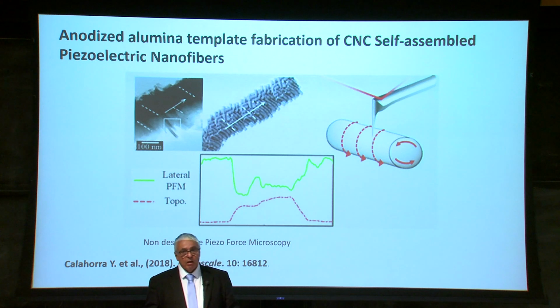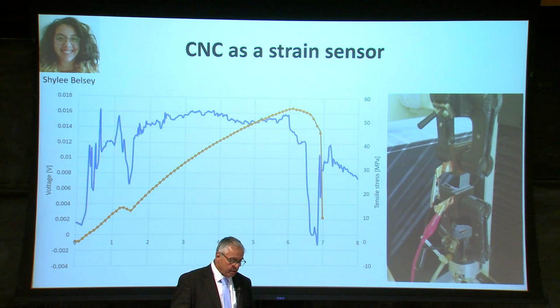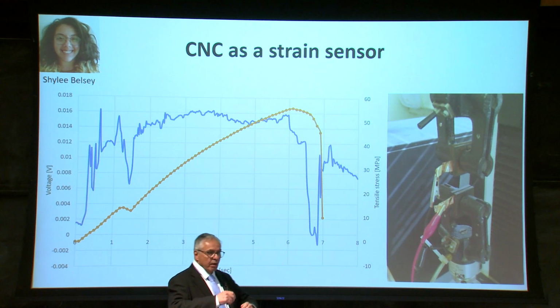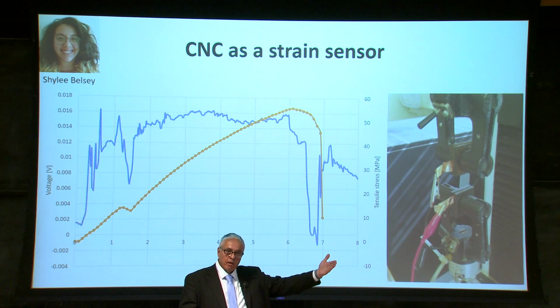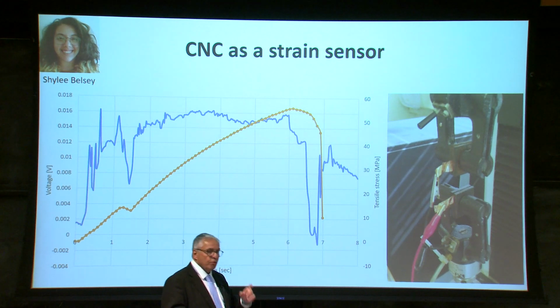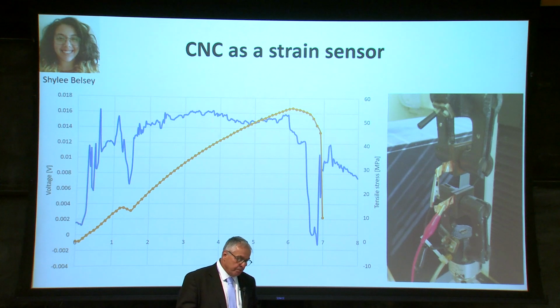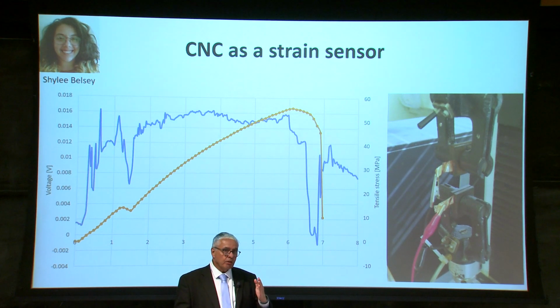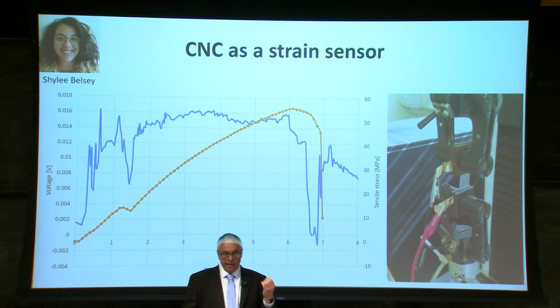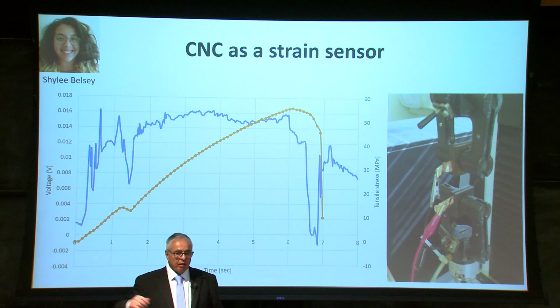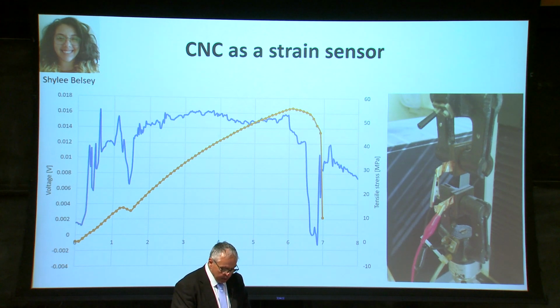Now, of course, came the question: will it also work on a large scale? So in this study, Shylee, one of the graduate students, developed just a regular cellulose CNC film, introduced it into an Instron, and started to pull and measure the force, which is in the red, and can be read by the Instron, and using two electrodes, measured the voltage that is produced. As you can see very clearly, the response curve for the voltage was much higher than the one in the Instron, which means that it's a very, very delicate strain gauge. In fact, Shylee reported that even if someone opened the door in the room, she could see a jump. So it's a very sensitive piezoelectric device.